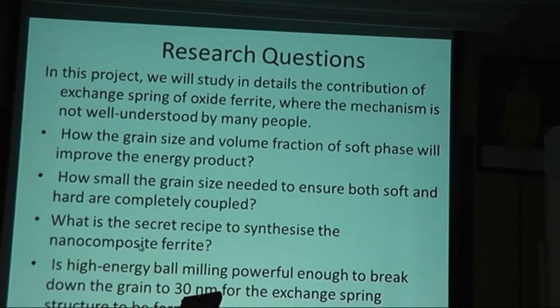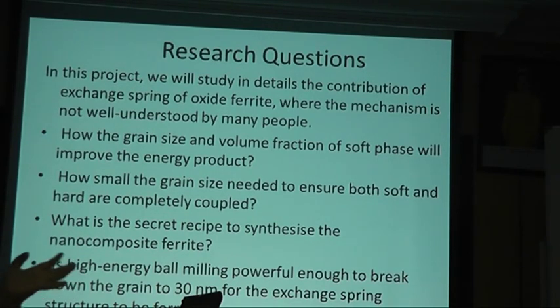Okay, these are the research questions, for nanocomposites and the NdFeB in metallic systems. The contribution of exchange spring is well understood, but not for nanocomposite ferrites. So these are a few research questions that I'm going to answer along the way. First, what is the optimum grain size and volume fraction? For NdFeB, theoretically, they found that for hard grain 20 nanometer, for soft 10 nanometer, and the volume fraction of soft is about 40%. 40% soft and 60% hard.